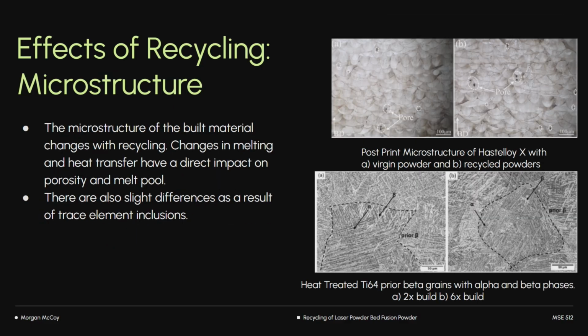As a result of the changes in laser melting, we have a change in the microstructure. They have a direct impact on the porosity and on the melt pool. On the top right, you can see that porosity is inherent in the laser powder bed fusion process, but with more recycled powder, you do see an increase in porosity.